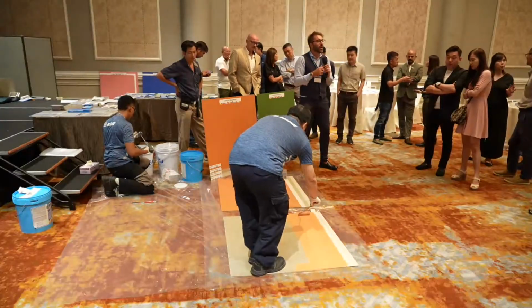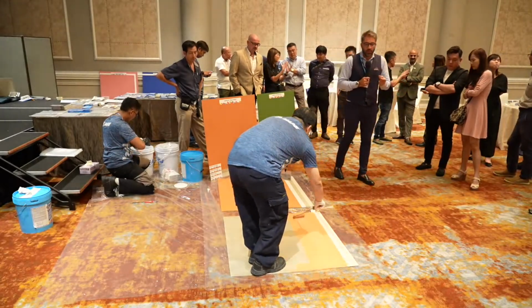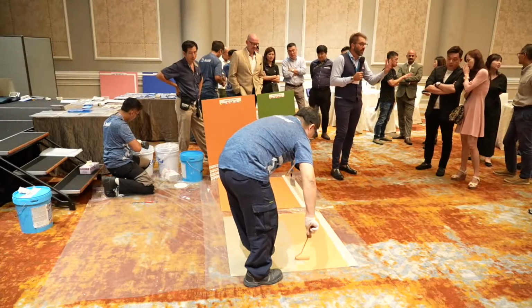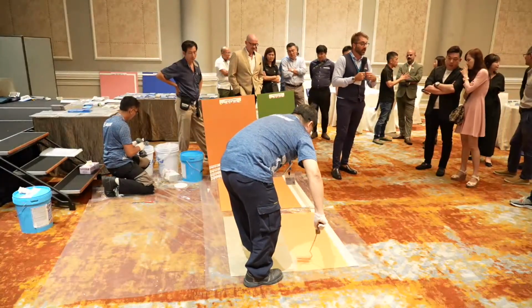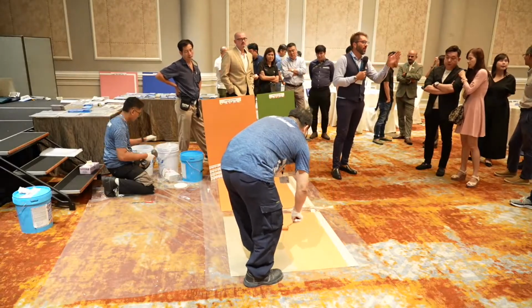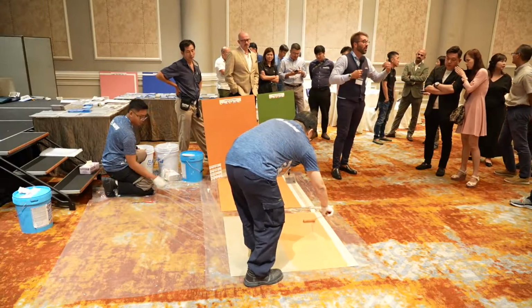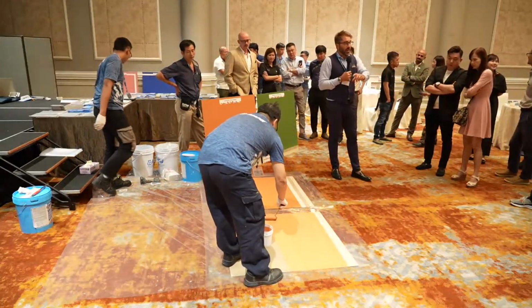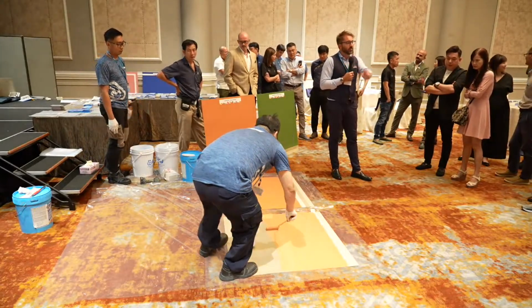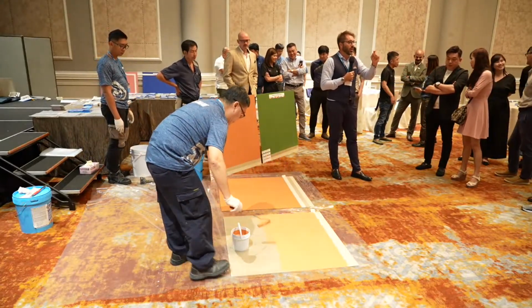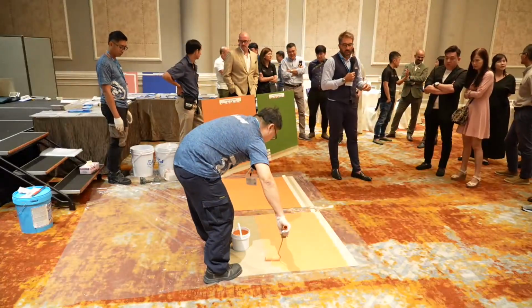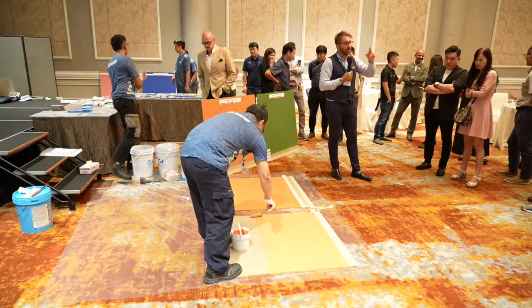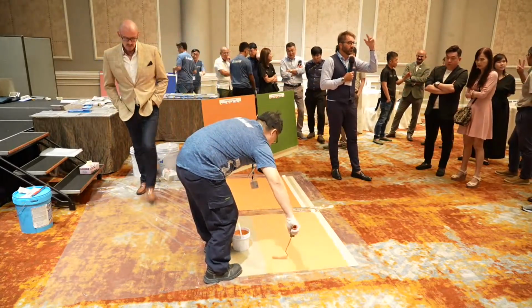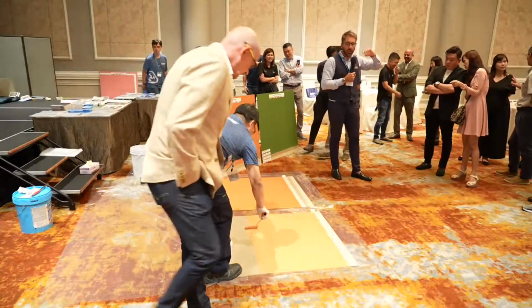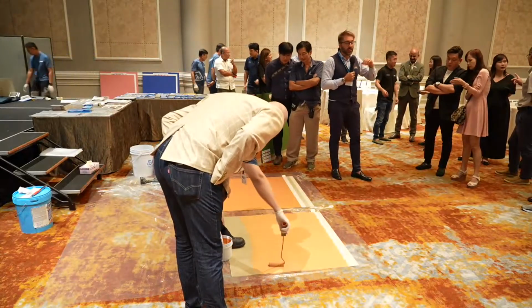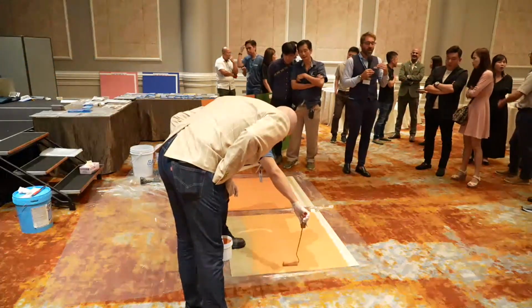It's a good location. We tested it also with, for example, our polyurea system for waterproofing, the liquid membrane that is really elastic, with 40-100% of elongation. We combine it with this product and also with the resin to see the crack bridging of the combination. And the crack bridging is in class B, that is the second class. Class A is really almost impossible to achieve, but class B is a really high position. That surprises us.